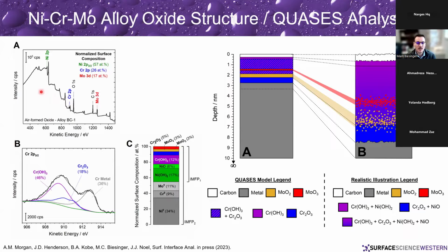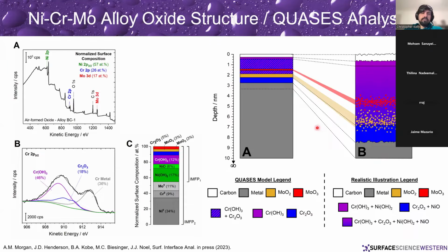And so you can put that all together along with what you've done with your survey scans, what you've done with your analysis, and we've been able to pull apart this oxide and hydroxide layer very effectively. And so we have our metal down here. We have a compact oxide, so something like some chromium oxide here. As we go up more near the surface, we have a mix of chromium oxide and hydroxide up here, till we have nothing but hydroxide at the surface. And then within these layers, we've got molybdenum 4 oxide in discrete positions in this layer, and molybdenum 6 oxide in this layer. And so in this layer that is only 2.5, 3 nanometers thick, we've been able to elucidate exactly what that layer looks like based on these types of analyses.